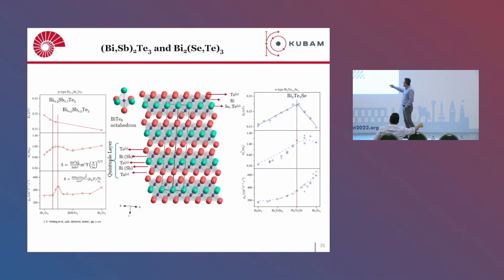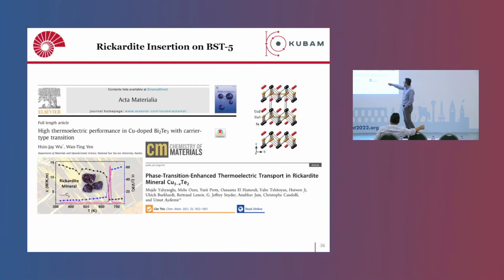So when we were dealing with this research, we found that there are a couple of research publications dealing with bismuth telluride doped with copper, getting better efficiencies. Now, we don't want to repeat that, but we have copper telluride, which can act like a copper source. At the same time, it shows a strange phase transition, and it is metallic. We thought, rather than using pure copper, why don't we use copper telluride?